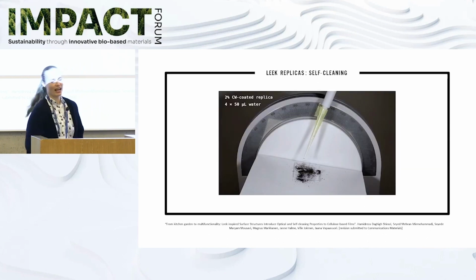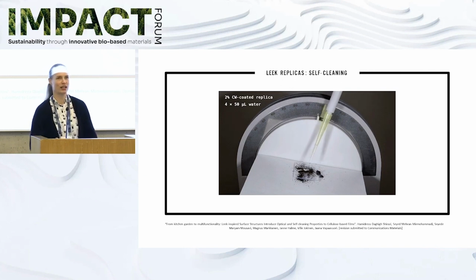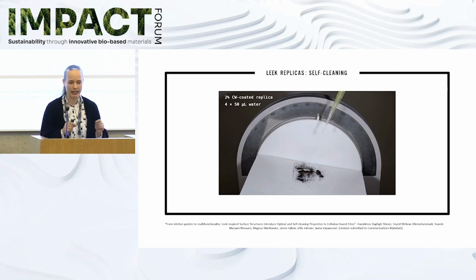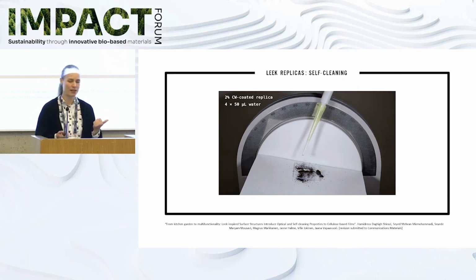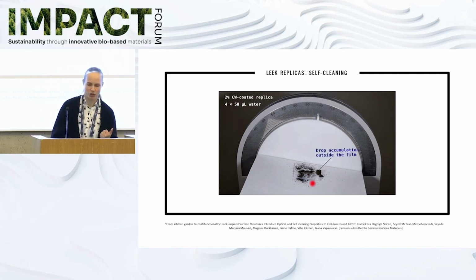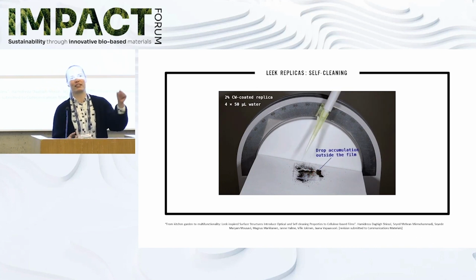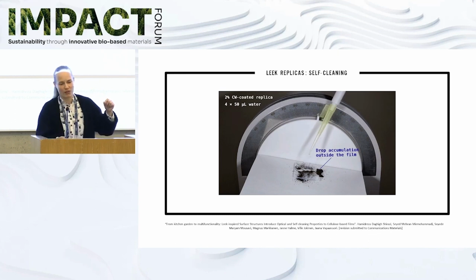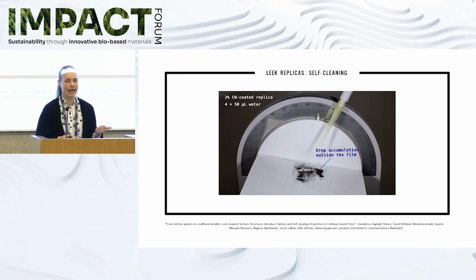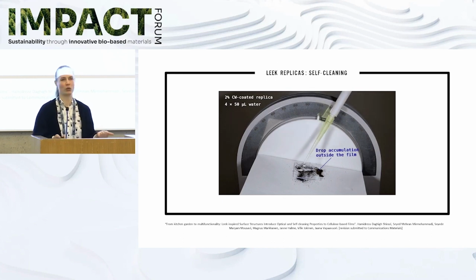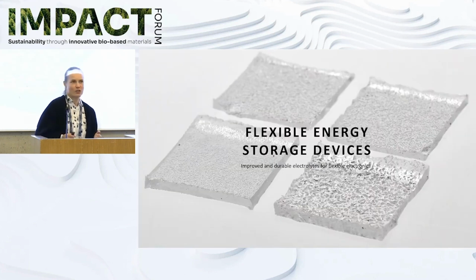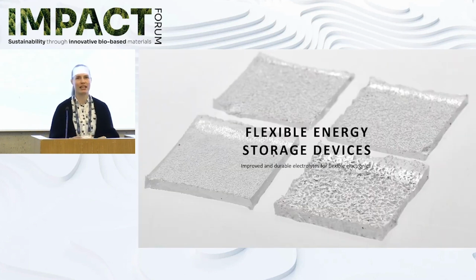Also, this added property was still there, so this is now the same property as on the leek leaves, but on a transparent substrate. So you can see this anisotropic wettability. The droplets start to roll onto a preferential direction, and they can then remove dirt or dust that has been accumulated on a solar cell. Okay, so this was my first case example.